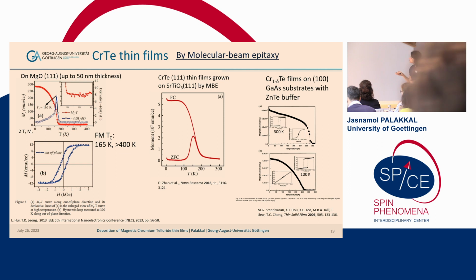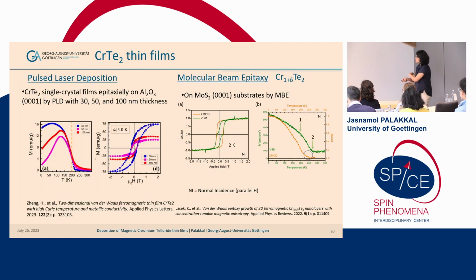And in this case, so this was CrTe, and I also checked for other films. This is the same for CrTe2 films. So here in this case, they were able to grow the CrTe2 film successfully by using PLD and found the TC. But when they grew it with molecular beam epitaxy, they found that this material again has a magnetic moment at room temperature. And here this is the XMCD result for the chromium spins. And here you see this small increase, and they suggested that this could be the starting of another magnetic phase.